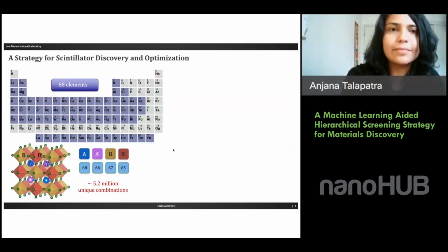To define the structural space of materials that we consider, we look at single and double oxide perovskites. We allow for mixing of up to 2 elements in both the A and B lattices. And to keep the problem tractable, we only look at 50-50 mixing. The idea being that if we do find some promising 50-50 compositions, we can always take a closer look at the full range of compositions for a particular chemical system. We also focus on cubic perovskites, even though perovskites are known to stabilize in other symmetries. We account for this separately, as I shall discuss later.